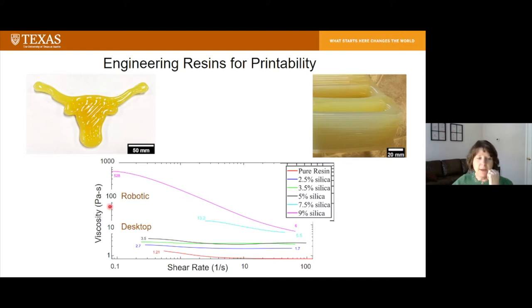One of the things we can measure is the viscosity of the material as it exits the nozzle. Here you can see some shear rate dependent viscosities of some of the materials that we're using. Our robotic system is capable of printing up to 100 Pascal seconds. The red on the bottom is pure resin, or EPON 8111. The viscosity there is so low that it doesn't hold its shape at all after it exits the nozzle.